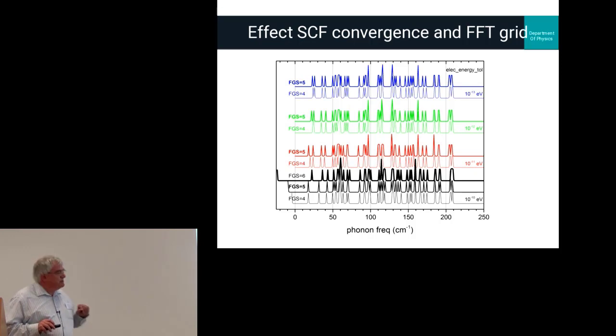Maybe we're going to have to do calculations to better than machine precision. That's not as hard as it might sound. The other feature I want to draw your attention to is the effect of the auxiliary grid for the density. This is using ultrasoft pseudopotentials. The potentials are moving across the grid. There is an eggbox effect contributing spurious forces. If we turn up the grid, this is a grid scale, the ratio of the g-max of the density grid to the g-max of the orbital cutoff, we have to go up to four or five to converge this out. So this is another important convergence issue.